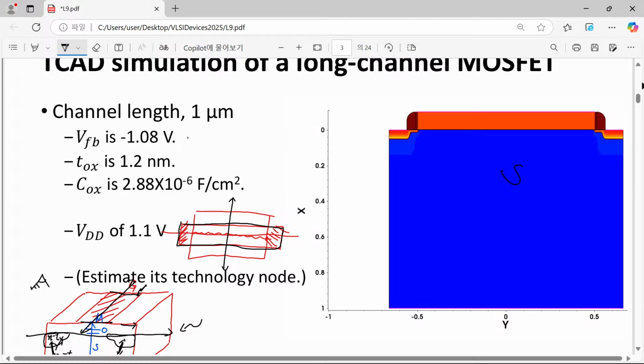The flat band voltage is around -1 volt, and oxide thickness is 1.2 nanometer. Please note that this number, 1.2 nanometer, is, I think, the thinnest one possible with just pure silicon dioxide. Using just a pure silicon dioxide layer, we were able to scale down our oxide thickness down to 1.2 nanometer. Of course, in reality, we can reduce its thickness even further.